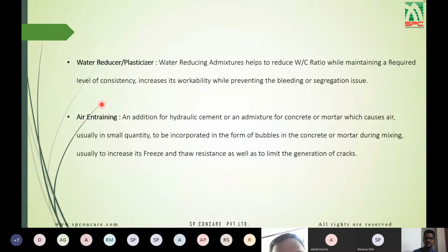Next is air entraining admixtures. So an addition to hydraulic cement, or an admixture for the concrete or mortar, which causes air, usually in small quantity, to be incorporated in the form of bubbles in the concrete or mortar during mixing. So when we add air entraining admixture into the concrete, it incorporates a small quantity of air bubbles. What happens when you incorporate these bubbles? It usually increases freeze and thaw resistance, as well as limits the generation of cracks.